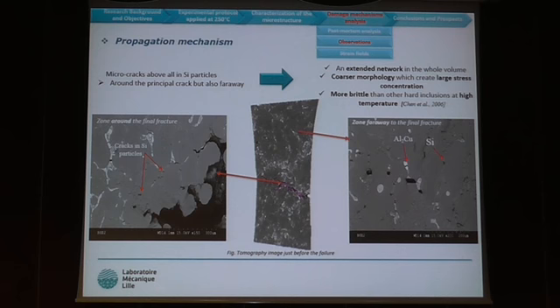If we continue to the propagation mechanism with SEM images, this is an SEM image around the final fracture, and here far away from the final fracture. You see in both cases there are these microcracks in the phases, but you see clearly it's more present above all in silicon phases, as you can see here. We can explain why it's more in silicon phases, because the silicon phase has an extensive network in all the volume. It represents the majority of the volume fraction, but also this silicon phase has a coarser microstructure which creates large stress concentration around these particles. And above all, these particles are more brittle than the other hard inclusions at high temperature. That's why you see more microcracks in silicon.